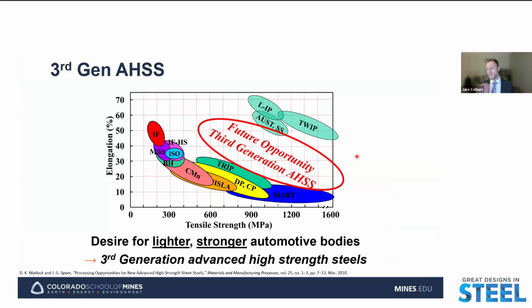To set up a little bit of the background, and why we are concerned with liquid metal embrittlement, we'll begin by looking at our elongation versus tensile strength plot for a range of first generation and second generation advanced high strength steels. As the automotive industry has worked to create lighter, stronger automotive bodies, that has pushed us into this area up and to the right of the first generation advanced high strength steels, where we now have these third generation advanced high strength steels.